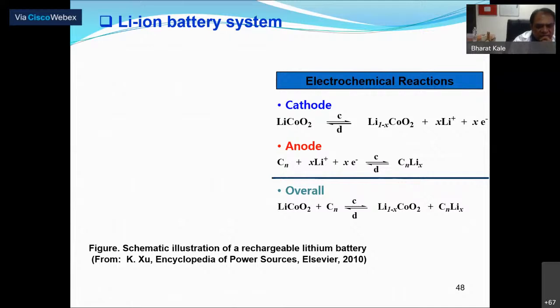This I already told, how this lithium-ion battery works. We have a cathode, which is lithium cobalt oxide, and the anode is carbon. While charging, we get lithium ion which goes to the anode, and one electron which is connected to the circuit. And again while discharging, the lithium ion is transported to the cathode along with electrons. So this cycle is connected to the electronic circuit so that the electrons are released. We get voltage and current. Actually, this reaction is basically the transportation of lithium from cathode to anode, anode to cathode. So that process should not be disturbed during cycling, and it depends upon your material quality and their structure.